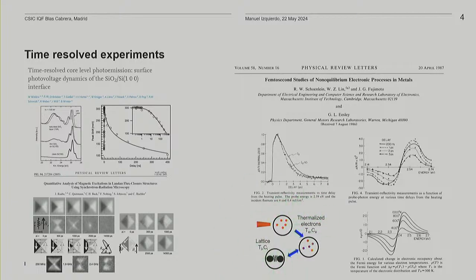this kind of model, the two temperature model, where they assume that the laser excites the sample, and then you have two baths. One is the electronic bath that gets very hot upon laser excitation, and then there is an exchange with the lattice. This information results from modeling. You can write some rate equations. However, you cannot really understand how electrons modify and how they transfer to the lattice and how the lattice changes.